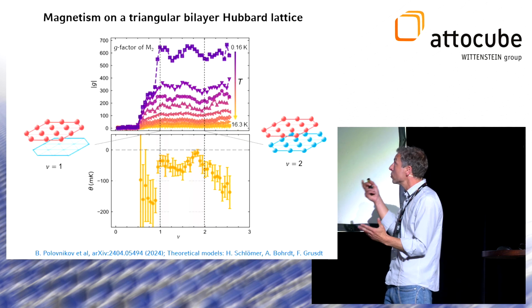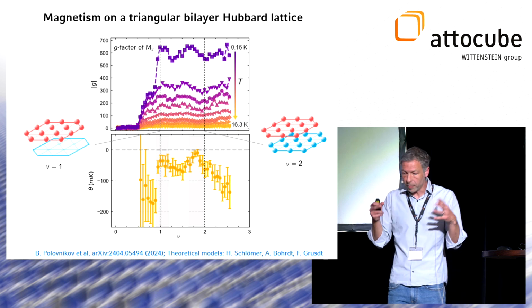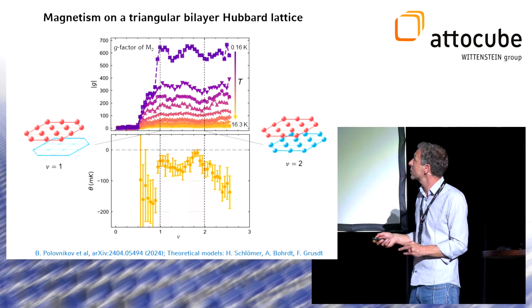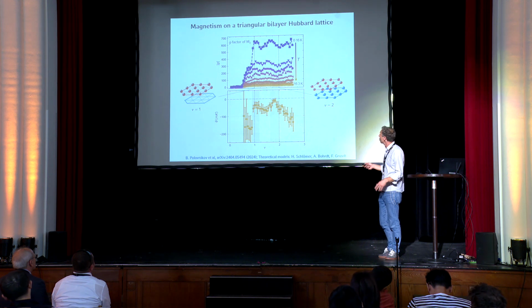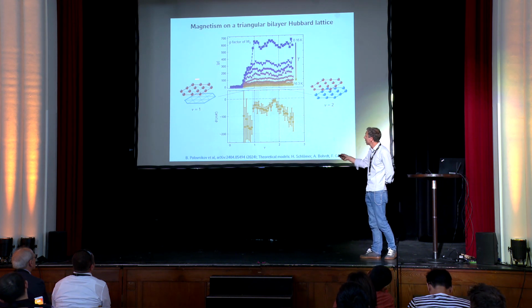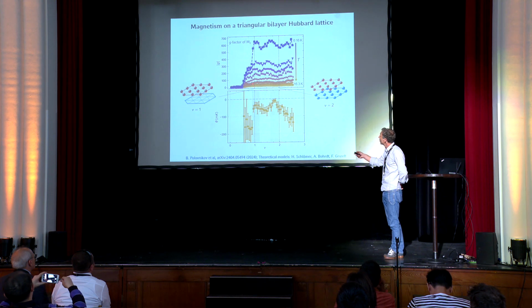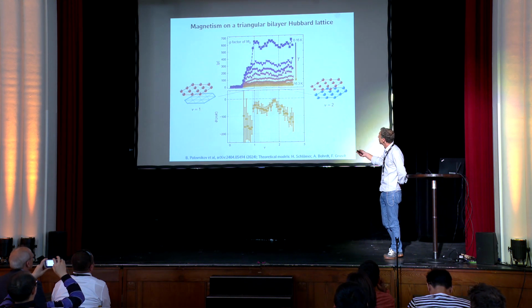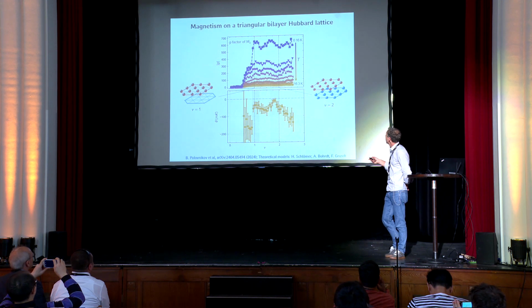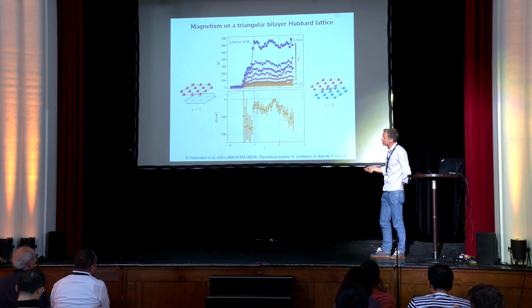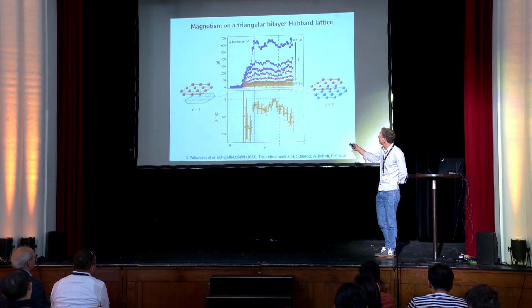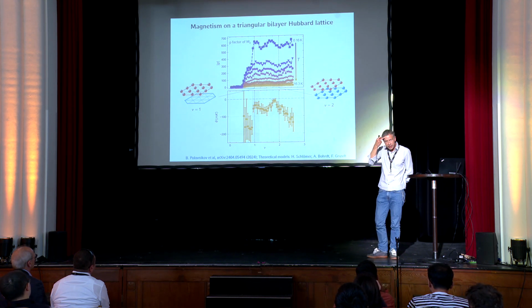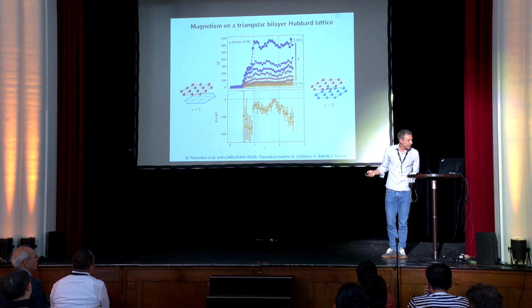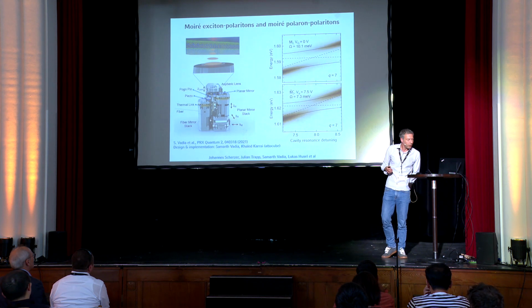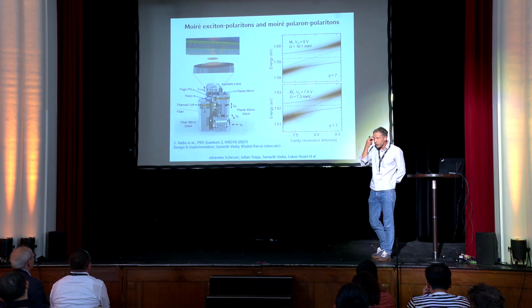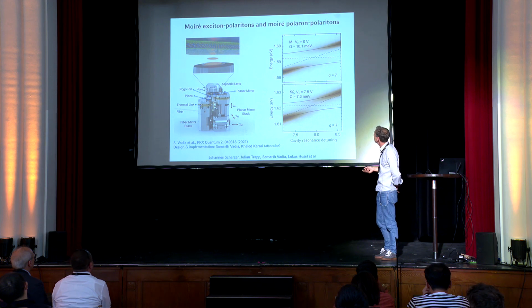And no surprise, and we have seen this in many previous talks, there is emergent magnetism due to correlations of spins residing on this lattice between the nu=1 Mott insulating state and the nu=2 insulating state. We see quite some variations in the magnetic susceptibility on the lattice, reflected by the g-factor of this secondary moiré exciton. I see my time is running up, but I would still like to point out the most exotic limit that we have realized today.